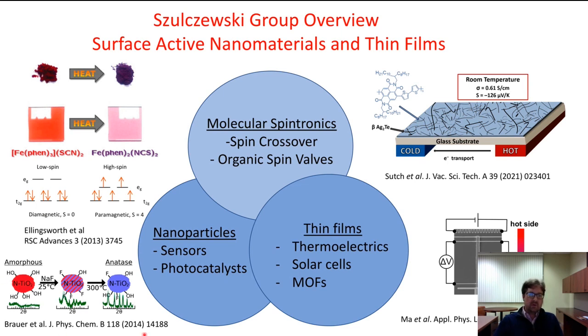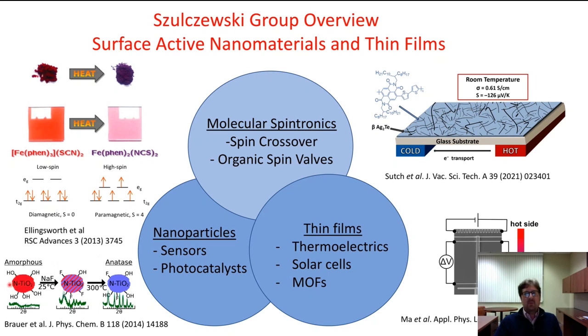If you draw your attention to the bottom left-hand part, we've made photocatalysts out of titanium dioxide — nanoparticles intended to catalyze reactions on the surface. We want a nano-sized material to have a high surface area. Titanium dioxide is a known photocatalyst, except it absorbs ultraviolet light. We chemically made these with nitrogen doping, which lowers the band gap and allows them to absorb visible light. Through chemical and heat treatment, we crystallize the material, which removes defects and replaces hydroxyl groups with fluoride, increasing the photo activity.